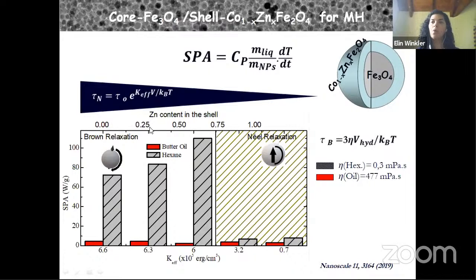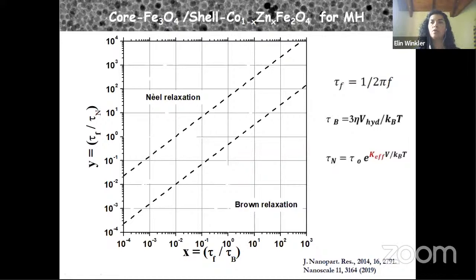So up to here, we proved that by changing the shell composition, we can tune the Brown or the Neel relaxation. However, what we want is to be independent of the viscosity. We didn't reach that either, so we have to make a step further. To do that, this kind of graph is very helpful, developed by Emilio de Bellasi and Enio Lima of our lab, drawing the relation between the relaxation times involved in the experiment.